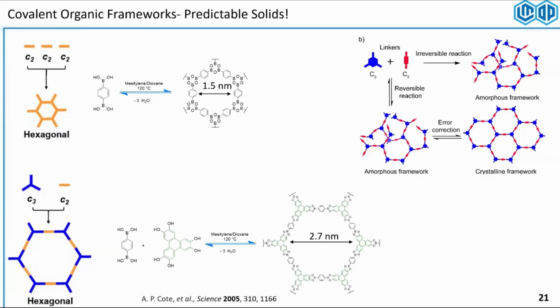For example, if we take a C2 symmetric building block, we use boronic acid condensation, which trimerizes these boronic acids. We put it in a reaction vessel, we heat it up, we will generate a hexagonal topology of covalent organic frameworks, which each one of the vertices have one of the same building block that we started with. If we take a C3 symmetric building block and a C2 symmetric building block, for example, this sort of transformation is called dioxaborole transformation. It's still reversible. We can make another type of Kagome lattice where now in each one of the corners you have a different precursor, in each one of the axes you have a different one.